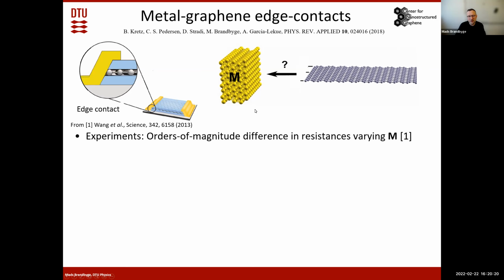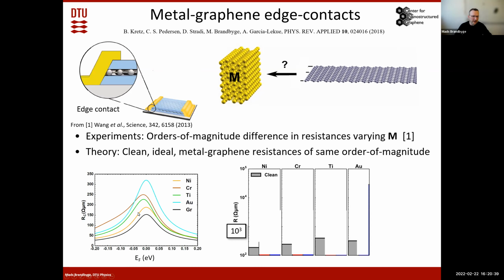So in the experiments, it's known that the resistance here changes by orders of magnitude when you vary the metal and also when you vary the processing steps. So we try to do calculations to figure out what goes on. If you just do a calculation of a completely ideal graphene metal contact at the relaxed bonding distance between graphene and metals, you see basically that the different metals, from nickel here to gold, have roughly the same resistance, within the same order of magnitude, maybe a factor of 2 or 3. So it will not be an ideal contact.